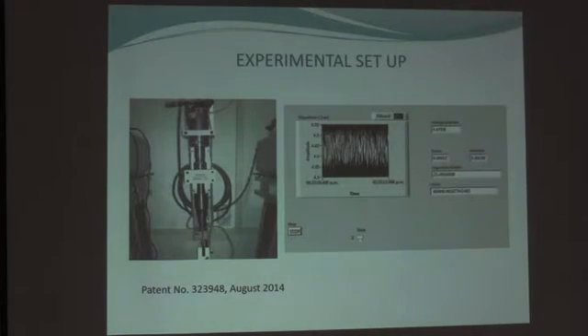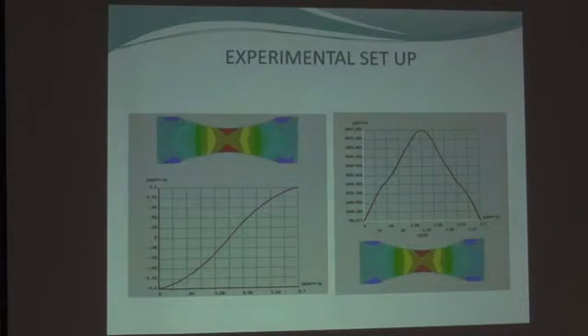It's about 110 degrees. Now, this is the ultrasonic fatigue machine which has been developed in my laboratory and patented in August 2014. It is very simple. We use a LabVIEW program to start the test and count the number of cycles, and it automatically stops the test when the specimen is broken. In order to carry out ultrasonic fatigue testing, it is necessary to fit the resonance condition. That means that a stationary elastic wave is developed along the specimen, inducing high displacement at the end of the specimen and high stress at the middle section of the specimen.